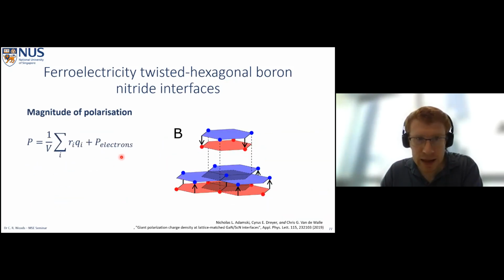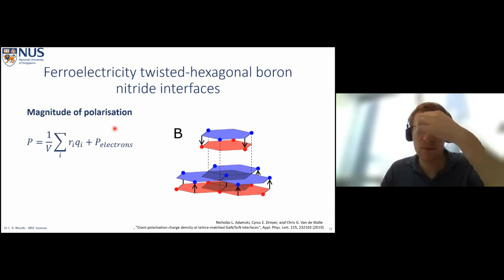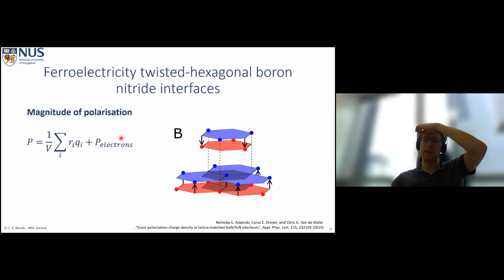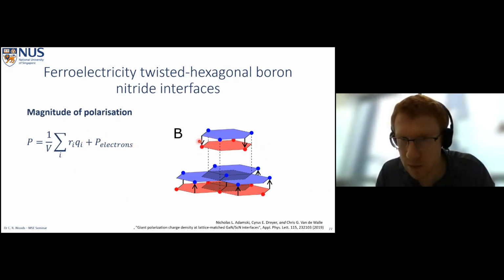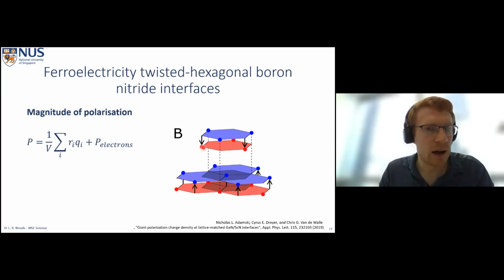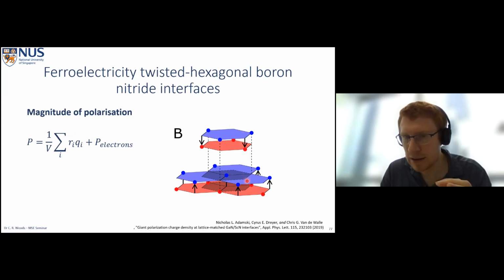And I then mentioned that actually this simplistic view misses off electronic wave functions. So if we can include this in our calculations, we get a better idea of how much we're deforming this, where this deflection is coming from. Because you could actually imagine that we could have this effect completely dominated by electronic wave functions. So the atoms just sit in plane as they are, but the electronic wave functions are the things which shift due to the van der Waals interaction with the layer below, and that could be the opposite of what I described, where the electronic wave functions are dominating over the atomic movements.